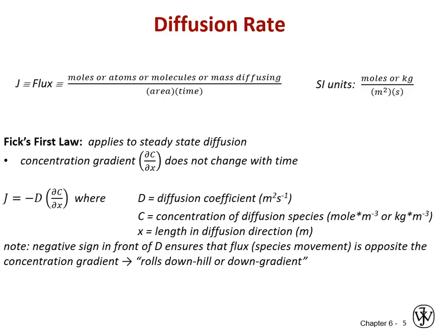Now, having defined that, we move to probably the simplest and most widely used model of diffusion, and that's called Fick's first law. It literally says that the flux of diffusing species is equal to the negative of a constant, called the diffusion coefficient, times the concentration gradient. So that's the change in concentration with unit distance. So it's not a time rate, it's a distance rate.